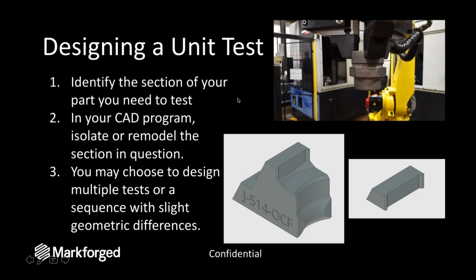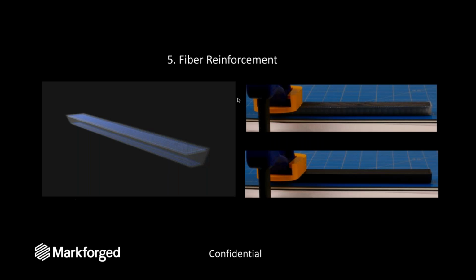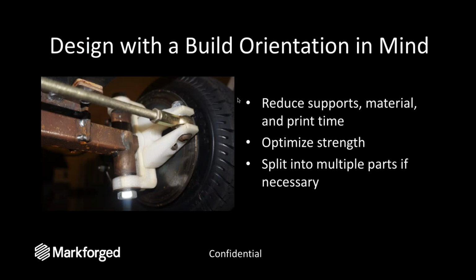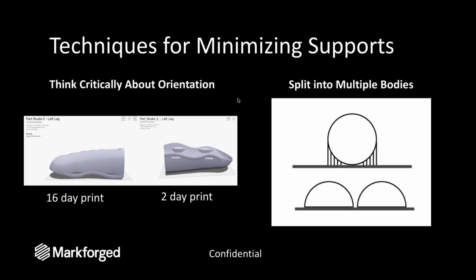Why exactly did the leg guard reduce the build time from 16 days to 2 days? So this is going back to orientation. The reason why this takes so long is that it has this big hollow cavity on the inside that fills up with support material, and even though the part itself does not change, the geometries aren't changing, it's the support material that's causing that big increase. So essentially you're filling the entire section underneath this contour with support material, such that when you flip it over, the only thing that's being supported is sort of the base features over here.